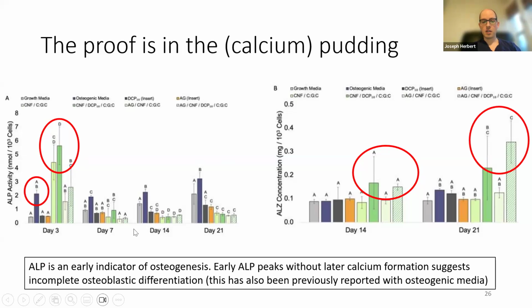And so when you look at our compound, we got this early spike of ALP, and then again, the proof is in the pudding. The actual calcium formation at day 14 and day 21 is quite high compared to the early ALP activity without a concomitant increase in the ALZ concentration. So it's probably getting incomplete differentiation of the osteoblast there, as opposed to our compound, which does seem to be successfully inducing osteoblastic differentiation, which is exciting.